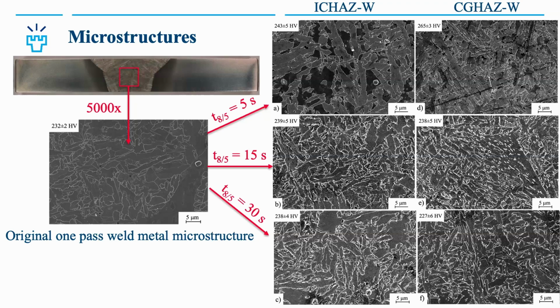And also, when we saw earlier the impact toughness results, the lowest impact toughness was in this intercritical heat affected zone with 30-second cooling time. And in this case, we can see that there are larger ferrite, like quasi-ferrite areas. So it might be that these are connected to the lower impact toughness in this.